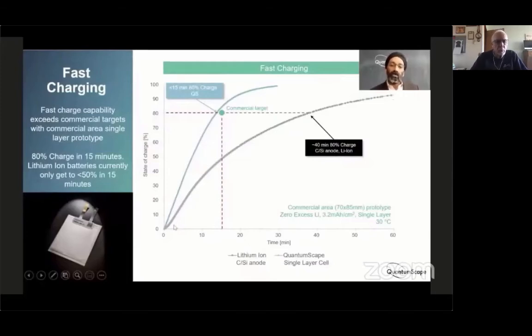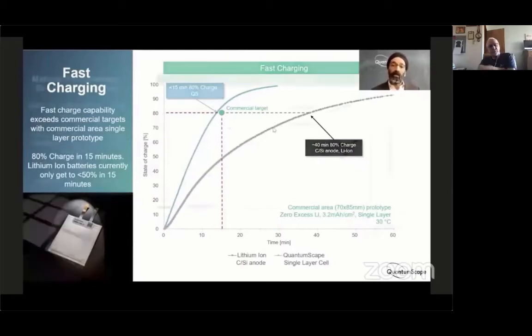Note that you can start charging these batteries at a relatively high rate of charge, but as the state of charge increases, you have to slow down that rate of charge in order to prevent dendrites from forming. With the QuantumScape technology, the solid-state separator already prevents dendrites. So there's no reason to slow down the rate of charge. You can start charging it at a really high rate and continue charging it at that really high rate until it gets all the way up to 80% in less than 15 minutes. This is not only better than any of the solid-state technology, but it's better than you can achieve with conventional lithium-ion batteries, which always have to manage this potential dendriting issue at high rates of charge.